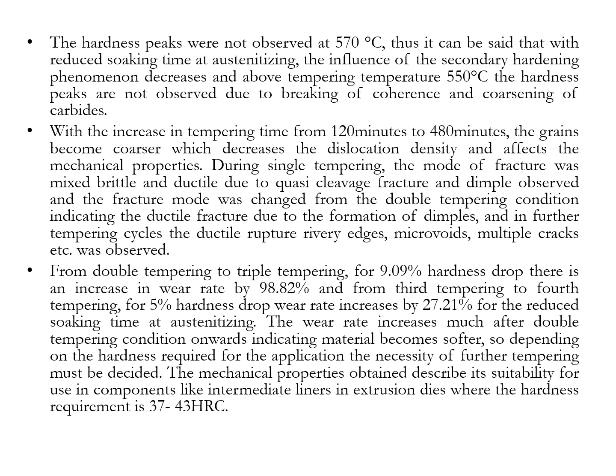With the increase in tempering time from 120 to 480 minutes, the mode of fracture changes from brittle to ductile. Wear rate was minimized at double tempering condition, and thereafter wear rate increases as material becomes softer.